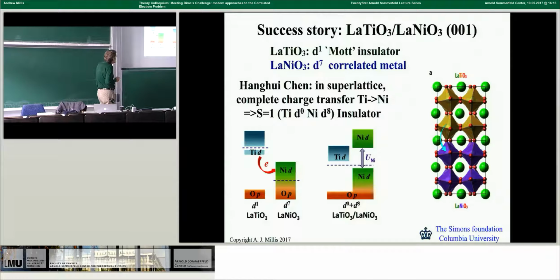All right. So Hanghui Chen, working with me, said that if we do something which is now possible in terms of material science, if I grow a superlattice of this material, alternating layers of lanthanum nickelate, shown here, and lanthanum titanate, shown here, and this is something that these experimental wizards can now do, then I should change the electronic structure in such a way that I go from having an insulating strip and a metallic strip to something which is completely insulating and which has had its electronic structure rearranged so that instead of being D7, lanthanum nickelate, the nickel becomes D8 as in nickel oxide, and it becomes a correlated or Mott insulator.